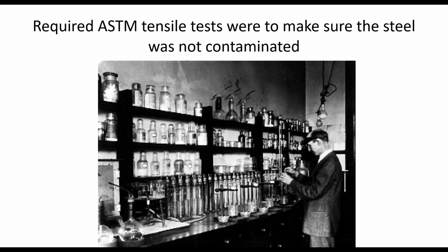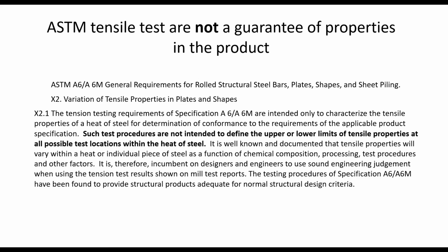Because in the 20s and 30s we didn't have the chemical analysis, how did I know that the steel I was sending you wasn't contaminated with something like tin or lead that I wasn't analyzing for? The way I made sure that the steel I sold you was what you expected it to be, able to do what it was capable of doing, was to check each heat of steel with a tensile test, because a tensile test was fast, quick, and cheap, and allowed me to demonstrate that we got the properties out of that heat of steel that I expected. And so the ASTM tensile test is a test of the steel heat, not a test of the products that I sell you. We see this even today.